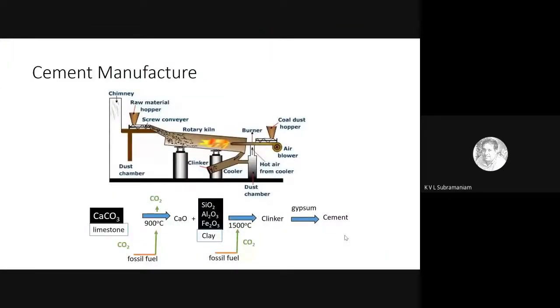The manufacture itself again requires heat and energy. So again, this is similar to what was done with the lime mortar. You actually have to free up the calcium from the limestone. So basically, the cement manufacture takes place in these rotary kilns, and these are massive drums. I'll show you photographs of these. And the raw material is basically limestone and clay, and that is added into this hopper, and the material comes into this kiln. And I'll show you what is happening in the kiln in the next slide.